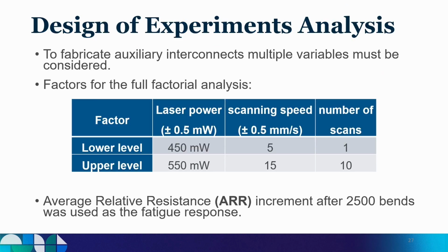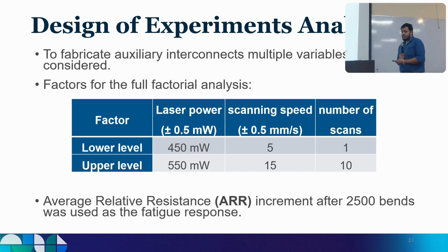And then to find out the parameters to use for auxiliary interconnects, I had to use a process called design of experiments. Design of experiments is a statistical approach. If you are familiar with statistics, I think you have heard of this. But if you have not, it is basically like a linear equation, but for multiple variables. So I used laser power, scanning speed, and number of scans. And my response is the average relative resistance increment, so the average resistance increment after 2500 bending cycles.